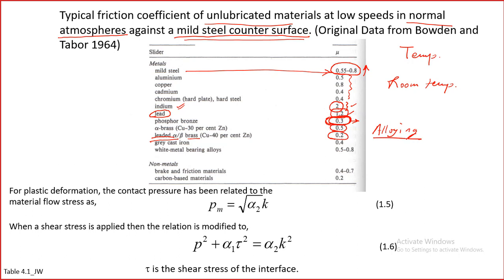For tribological application, you can select the alloying element you want in that metal so that you can get low dry friction, which is very important for any bearing. Even if you are using lubrication, it doesn't matter. You want low dry friction because the lubricant doesn't always work. It fails many, many times, and therefore dry sliding will always occur. Cast iron is also used as a good tribological material. Although you see here 0.4, many cast irons will give you a lower coefficient of friction, 0.3 or lower. Similarly, white metal bearing alloys. There are many types of white metals. This gives high friction, but there is another white metal called Babbitt material or Babbitt metal.